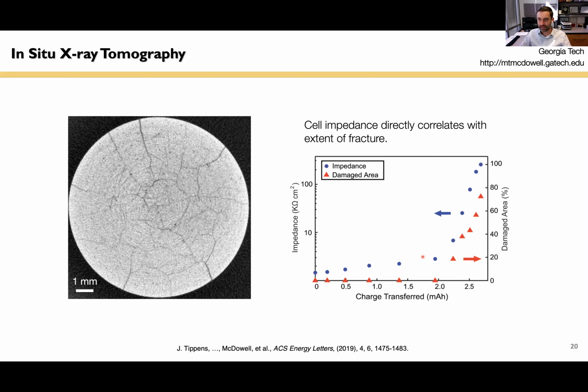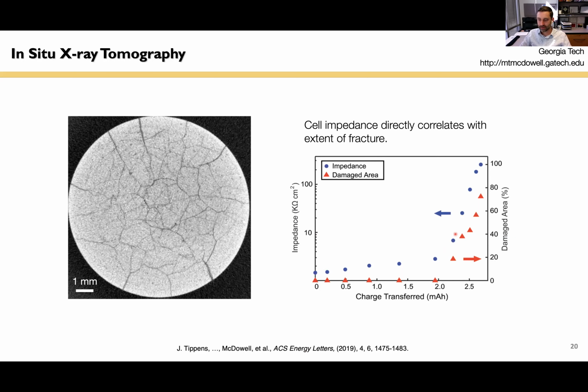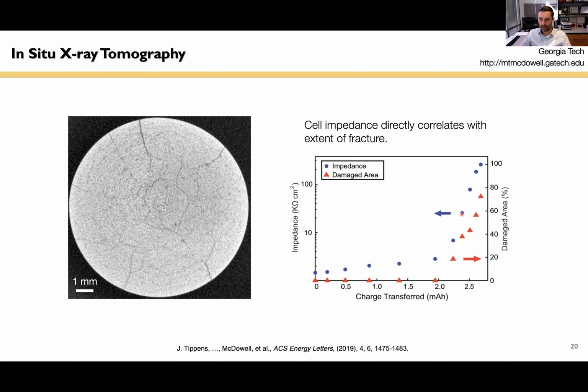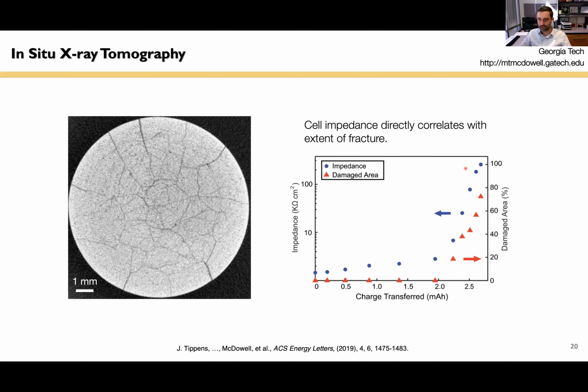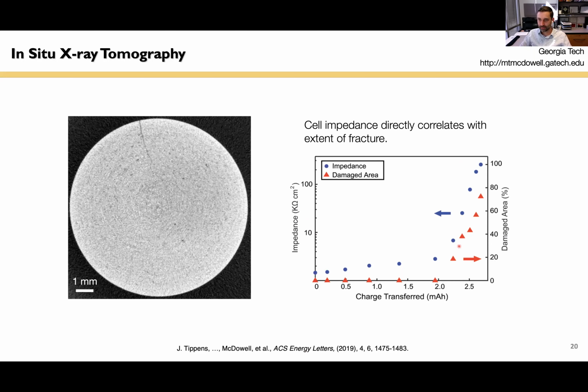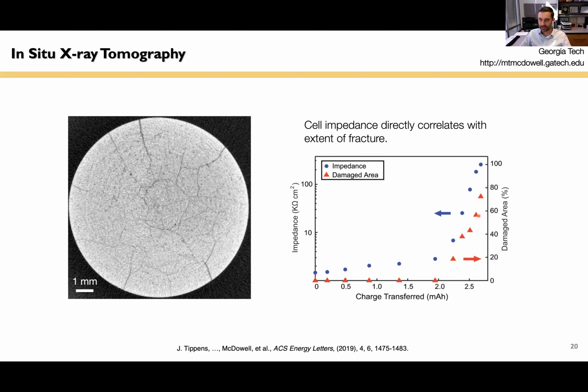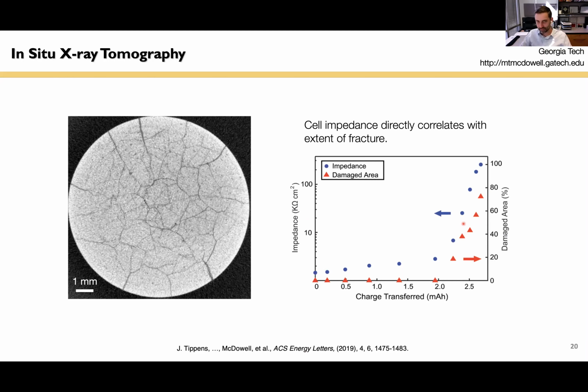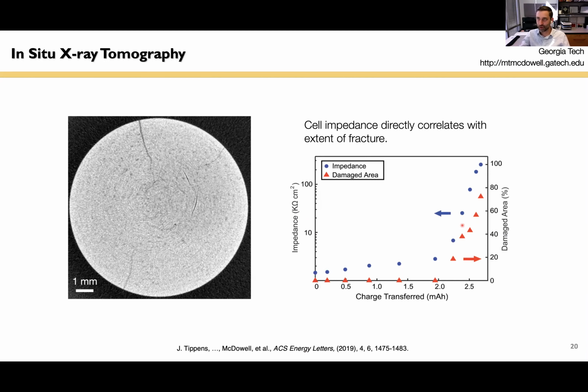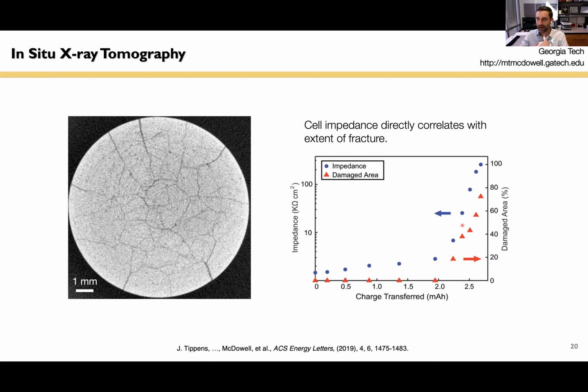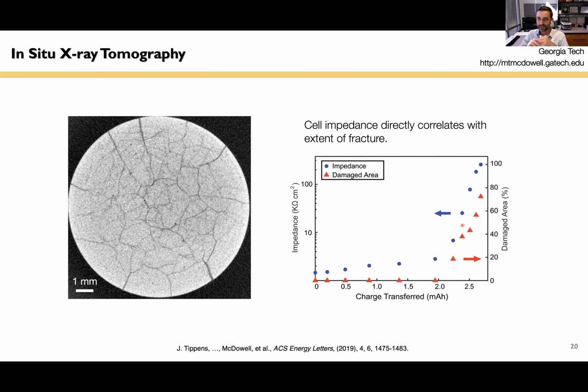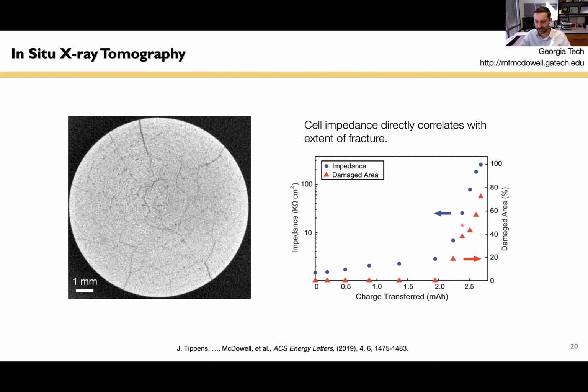So you can see that the impedance in the blue points here corresponds to the y-axis. This is increasing dramatically only when we start damaging the material through fracture, which is shown in these red triangles. So that makes sense. I mean, cracks cause impedance increase because they prevent ion motion. But there's a little subtle thing here that's interesting.